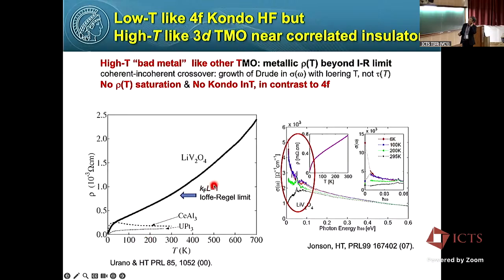But take a look at the high temperature, they really look like other correlated 3d transition metal oxides. For example, the high temperature resistivity is metallic. But as you see, let's say like 1 milliohm centimeter, it's actually beyond the Ioffe-Regel limit. So actually, this looks like metallic, but it's not really metallic. This is kind of incoherent transport. And if you look at the optical conductivity around this temperature, you don't see any Drude response, just a broad one. And with lowering temperature, a Drude-like component grows. So the system is getting a kind of coherence on cooling.